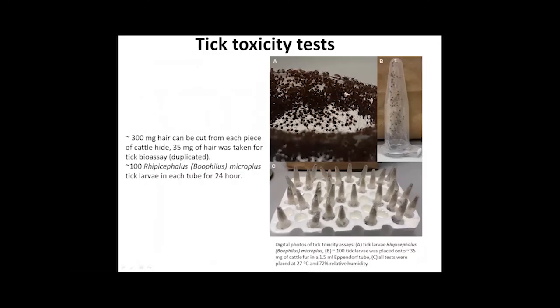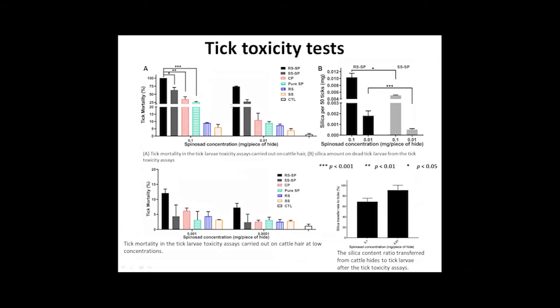In order to investigate the effectiveness of nanospinosad under simulated field conditions, four formulations, rough and smooth nanospinosad, pure spinosad, and the commercial product Extinosad, were compared. The tick toxicity test of the four spinosad formulations was evaluated using a modified tick larva assay, shown here, using cattle hair as the substrate. The tick toxicity results are summarized in Figure A. Pure silica nanoparticles showed little toxicity towards the tick. And the sample RSSP, the rough nanospinosad, demonstrates significantly higher tick toxicity than all the other three formulations in a wide range of initial spinosad concentrations from 0.1 to 0.001 milligram per cattle hide piece.